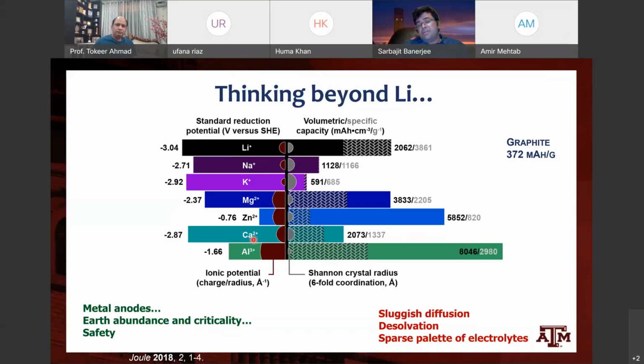Magnesium and calcium are perhaps two multivalent chemistries that have received a lot of attention. And I'm going to spend a little bit of time thinking about magnesium. One of the advantages of magnesium, of course, is very directly obvious to you. Lithium is 1+, magnesium is 2+, so you might be able to double the capacity accessible by going from 1+ to 2+, right? On the magnesium metal anode side, similarly, because you've got a 2+ ion, you can access a very large theoretical capacity.